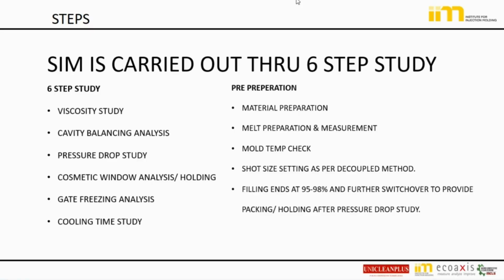We'll be injecting the part at a certain speed. Suppose I'm refilling 50 mm and my switchover is at 10 mm. From 50 to 10 mm, I'll be injecting at a speed. The moment the cavity starts filling and reaches about 98%, suddenly the pressure rises in the cavity because it is going to fill. That pressure exerts force on the screw, the transducer measures it, and it is shown on the machine. That is known as the peak pressure. That is very important for the viscosity study.